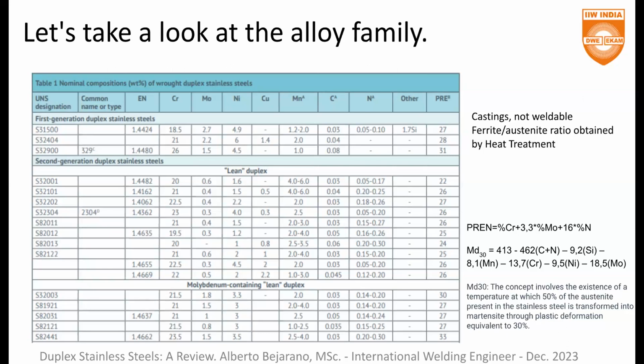And this temperature, because this phenomenon happens at a specific temperature, is calculated by using the percentage of carbon, nitrogen, silicon, nickel, molybdenum, chromium, and manganese. Okay, this is quite important in this case for this lean duplex.